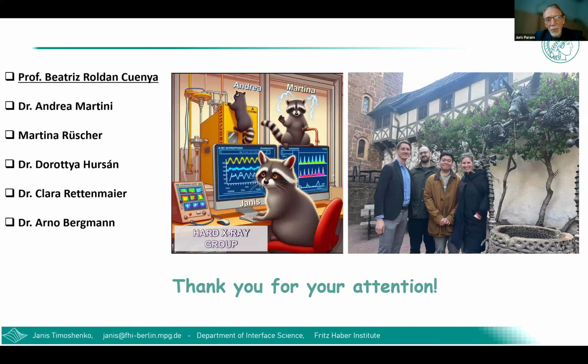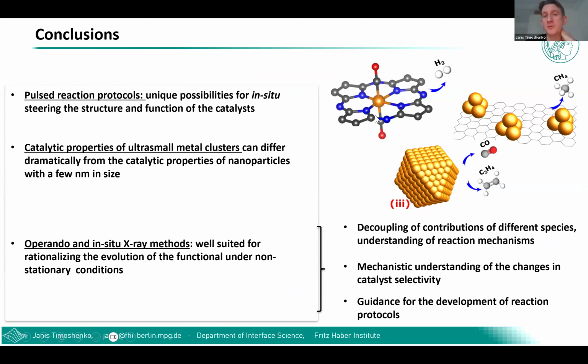So the original catalyst has copper incorporated into this carbon structure. This carbon is sort of distorted, amorphous, ill-defined. The loading of copper we can estimate, like I said, at below 0.1 milligrams per square centimeter. During the reaction, copper loses its position, this porphyrin-like position, and moves to form copper nanoparticles. They still seem to be interacting with the support, because otherwise they would not be pulled apart once we remove the potential. So we believe that the key to this reversibility is this particle-support interaction.